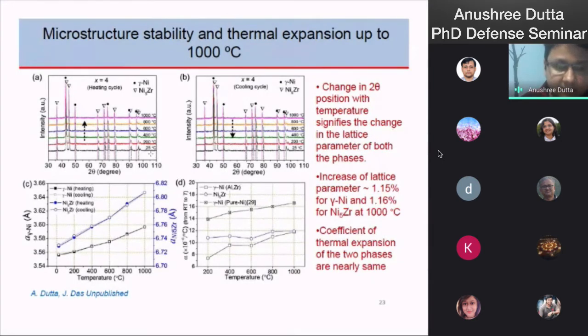The X-ray diffraction pattern from 25 degrees centigrade up to 1000 degrees centigrade is given here. The XRD analysis shows that the peak position for both gamma nickel and Ni5Zr shifts towards the lower theta value with increase of temperature, whereas the peak position reaches their original position during the cooling cycle from 1000 degrees centigrade to 25 degrees centigrade.